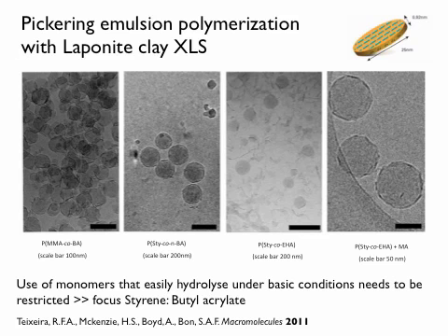But if you then change butyl acrylate for something more hydrophobic, ethyl hexyl acrylate, there is no affinity for the platelet to lie on the surface. So now what you end up with is a bunch of almost naked particles. Sometimes there's a platelet attached to it, and a lot of clay left in the water. If you would turn this into a material, this would give you a lot of bad properties. Because when you film form this, and we talked about film formation yesterday, all the clay would just clump together and you get big cracks. Whereas in these 2 cases on the left, you get a beautiful honeycomb type of structure,